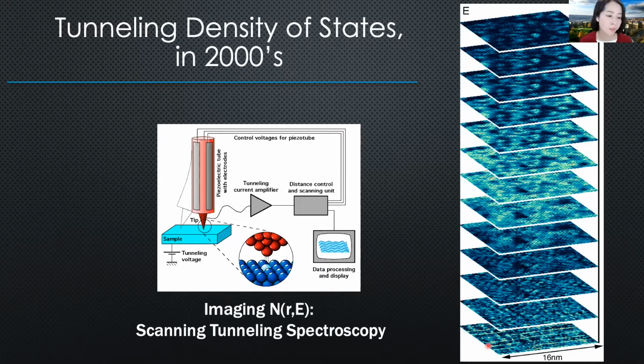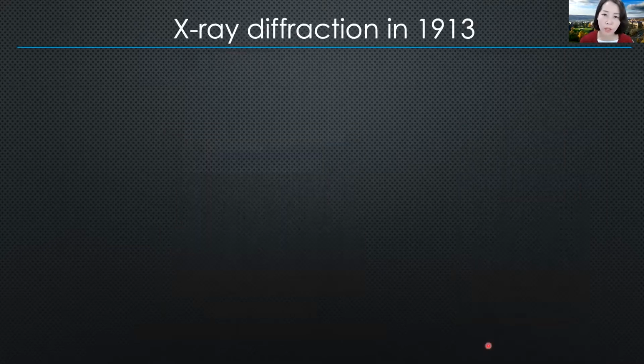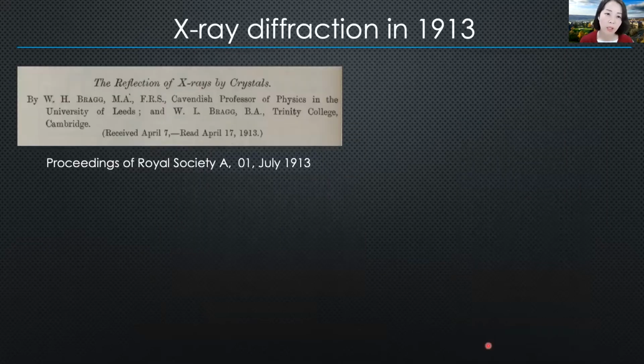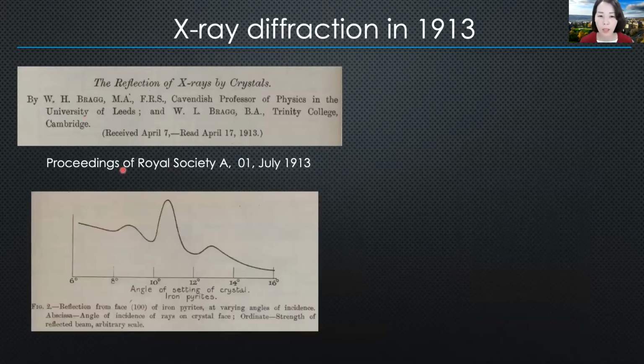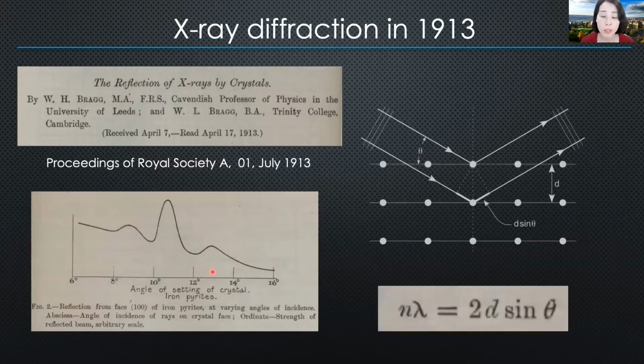In reciprocal space, X-ray diffraction in 1913, X-rays had been around for a little bit at this point, but it was this paper by father and son Bragg and Bragg where they had a first successful interpretation and analysis of this data. They had the very first successful forward model, which is to guess what you cannot see by your eye: that perhaps there are atoms forming a lattice like this.